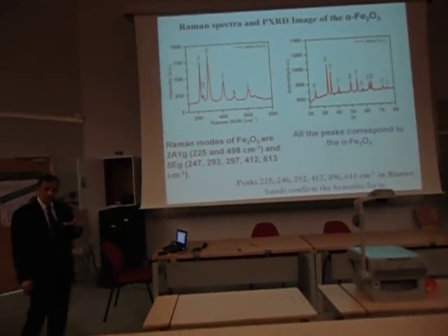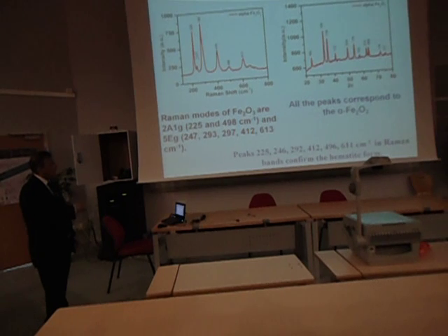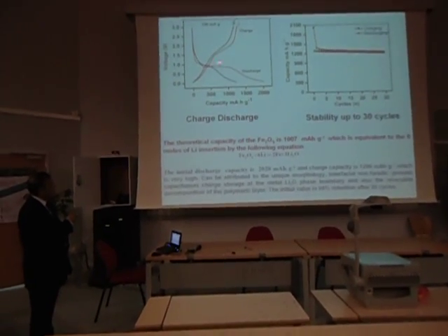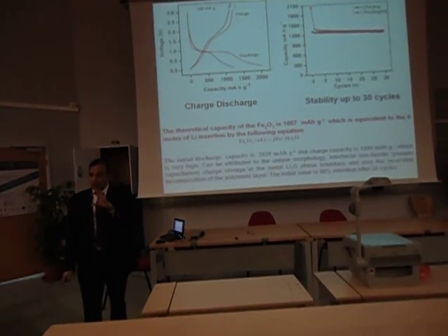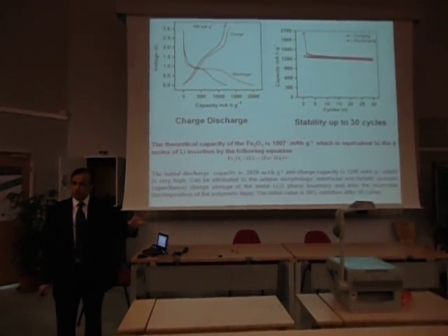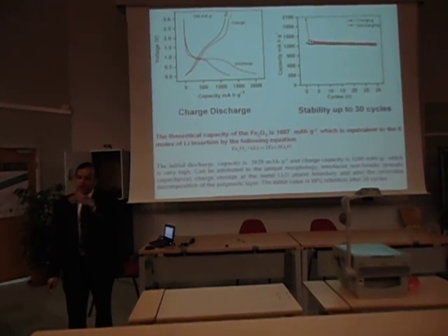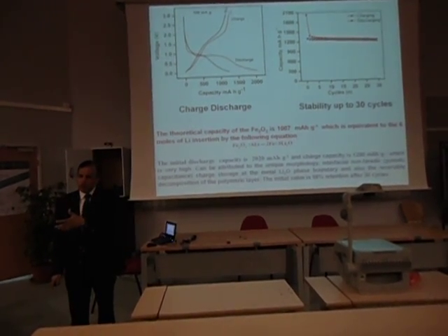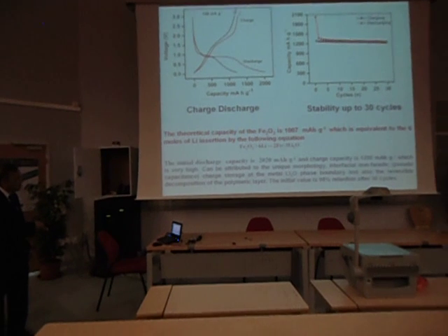We have also done other things. If you look at the same material, by using a MOF but heating it in an oxidizing atmosphere, we generate Fe2O3, which is highly porous. And you can see that we get very good battery characteristics in this way. So the same material, you start with MOF, metal organic framework, crack it in argon, a reducing atmosphere, and you generate a magnetic Fe3O4 carbon composite. In the other case, you do it in the oxidizing atmosphere, and you generate a highly porous Fe2O3, used for battery or storage applications and so on. Very interesting things can be done in this way.